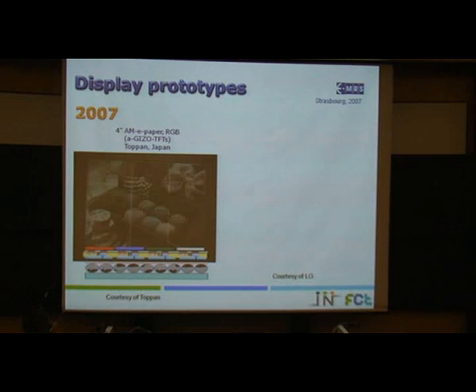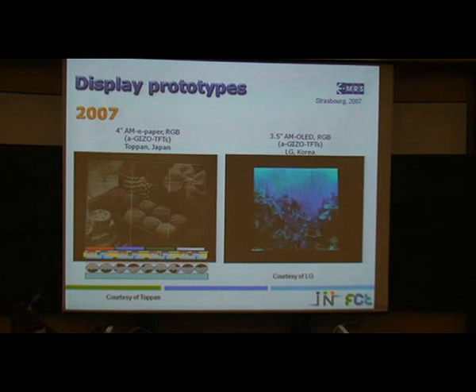And more recently, Toppan, because now e-ink, this type of electrophoretic display, is very widely used, because the cost associated with the production of this type of display is very low. They presented a display using the e-ink technology, also using amorphous gallium indium zinc oxide TFTs. This display has 4 inches. And LG also presents a display using the same type of amorphous gallium indium zinc oxide TFTs, a display with 3.5 inches diagonal using OLED technology, a more expensive technology.